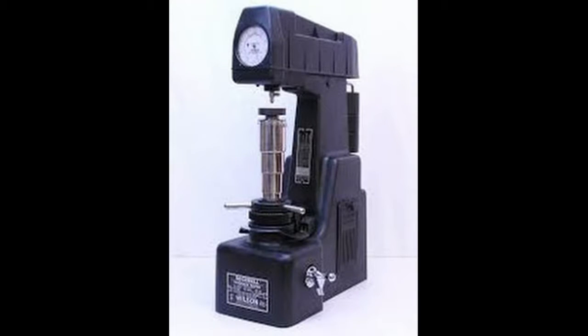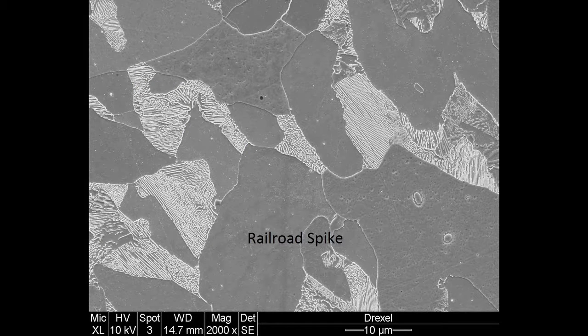Rockwell hardness testing and SEM microscopy were performed on each of these samples in order to observe the evolution of the microstructure throughout the process. The initial microstructure of the railroad spike is composed of colonies of pearlite in a ferrite matrix, typical of a steel with a carbon content below the eutectoid composition.